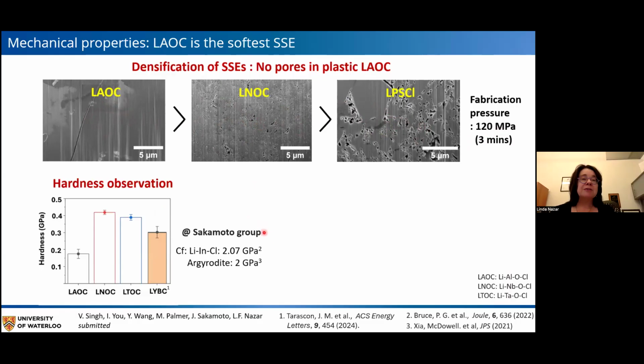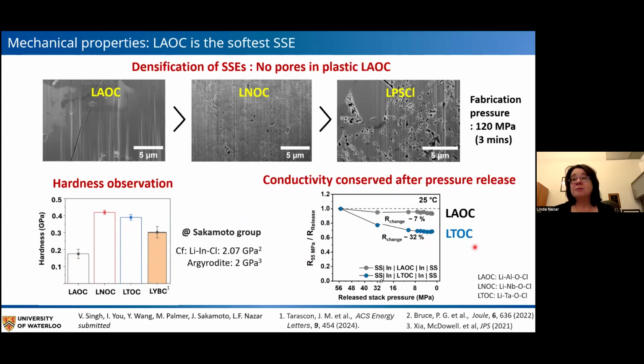And Max Palmer and Jeff Sakamoto's group measured the hardness of some of these materials, and you can see that LNOC and LTOC are about 0.4 gigapascals compared to argyrodite, which has been measured by Matt McDowell's group to be around 2, and LAOC is even much lower at less than 0.2 gigapascals. And Vipin Singh in my group, who's been working on these materials for some time, also has just shown, when we're measuring resistance versus stack pressure, that when you release this for LAOC, again, there's very little change in the resistance, whereas for the lithium tantalum oxychloride, there's a distinct difference. So this, as I said, really is viscoplastic. The LAOC is, and LTOC is not.